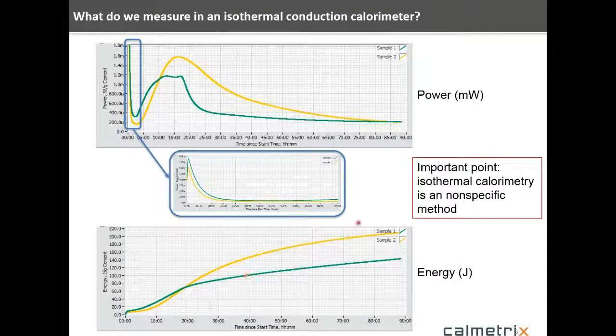It's a good spot here to point out that this technique is considered a non-specific method. And what does that mean? It means that the calorimeter doesn't care where the heat's coming from. All it knows is that the sample is generating heat. But if you've got 2 or 3 or more processes going on, it can't necessarily differentiate. So it can tell that there's heat coming off the sample, but it can't necessarily say that the reason there's this bump in the curve is because of a specific bacteria or whatever.